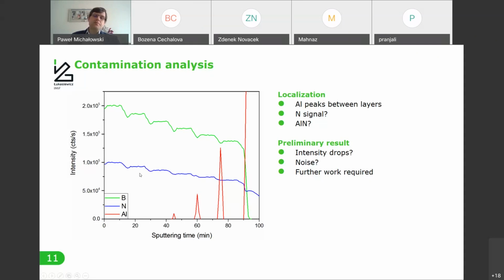So we expect to prove that actually during the growth process, some small crystals of aluminum nitride are residing between the boron nitride layers. Here you can see that the actual depth resolution is really extreme, because this is a single atom thick layer, and we can also detect some traces of elements which are between these layers. But as I said, this still requires additional work.